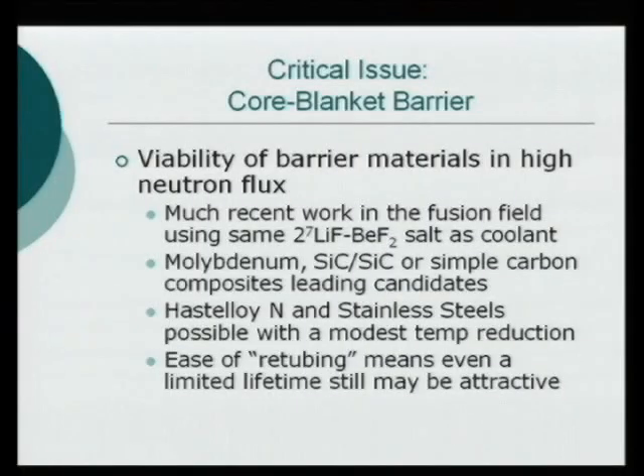The critical issue though is this core blanket barrier, this barrier between the two, and that's something we'd have to verify. But we benefit from the fact that there's a lot of work in the fusion field that has a lot more funding using these same salts as a coolant, and they have that first wall that is the most hostile environment you can possibly imagine.